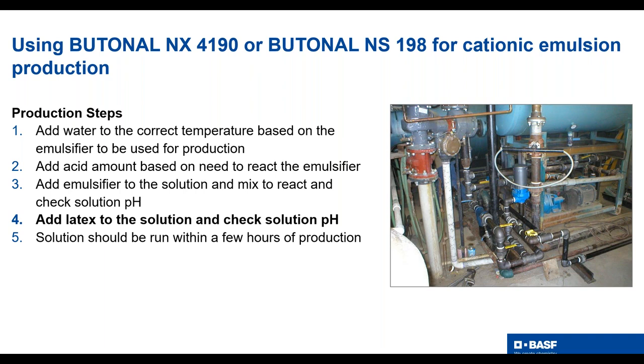One point I'll make is that latex can be injected into the solution when you're making microsurfacing, but you want to make sure that, again, the pH is very, very important to be able to measure. So you want to have some way of measuring that solution pH after the latex is injected into the solution on the way to the mill. That is a good process and it can be done.